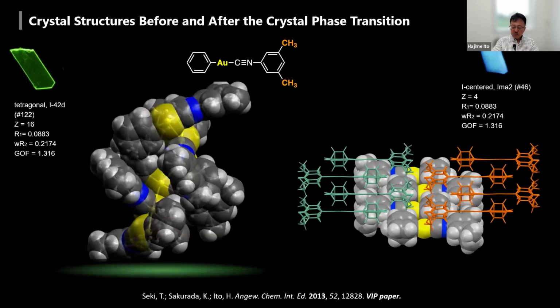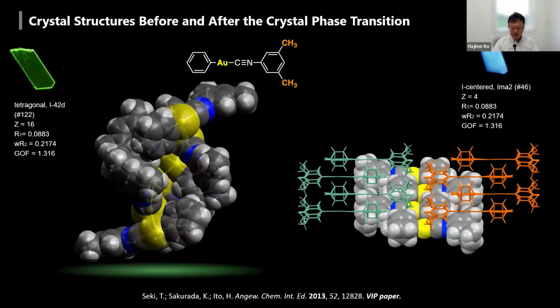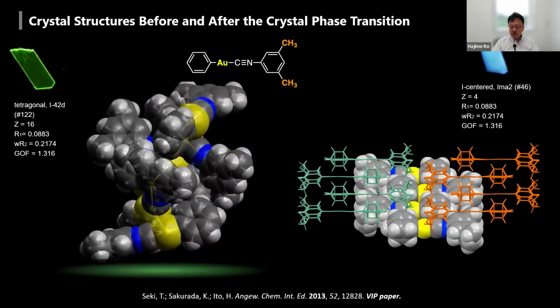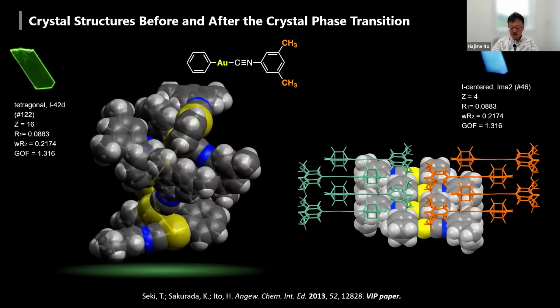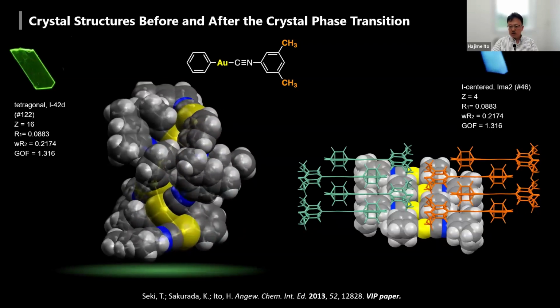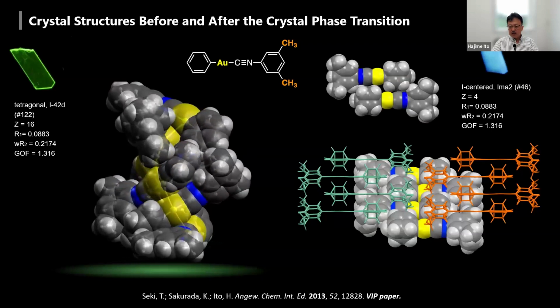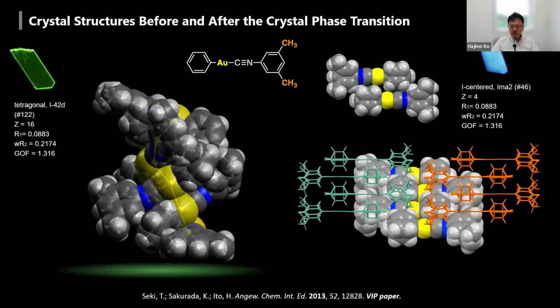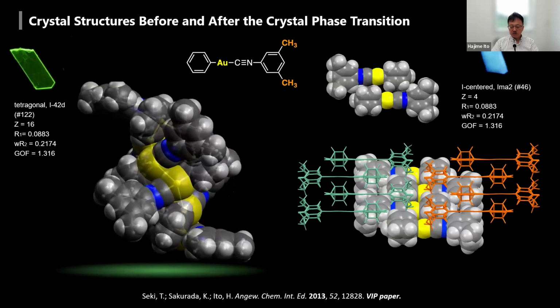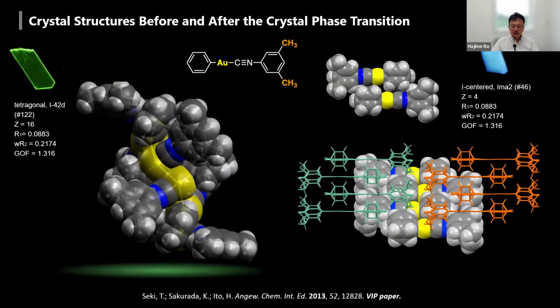This is the crystal structure after the mechanical stimulation. You see all molecules were crystallized as layer-by-layer structures. In these structures, aurophilic interaction disappears. Instead of aurophilic interactions, CH-pi interaction was generated in the new crystal phase.